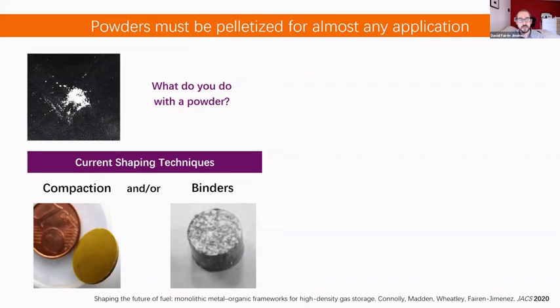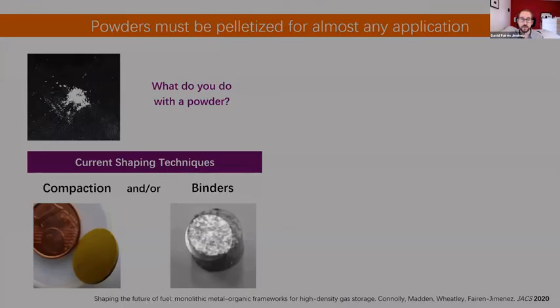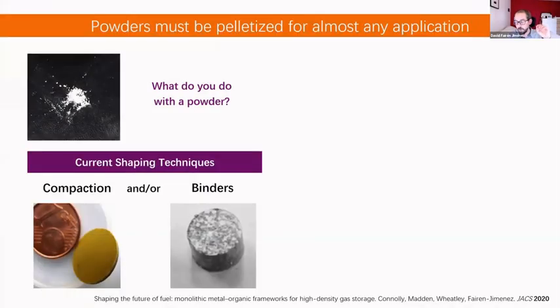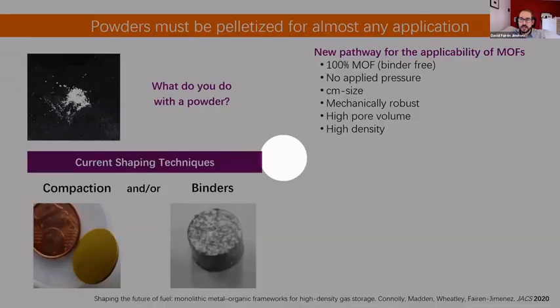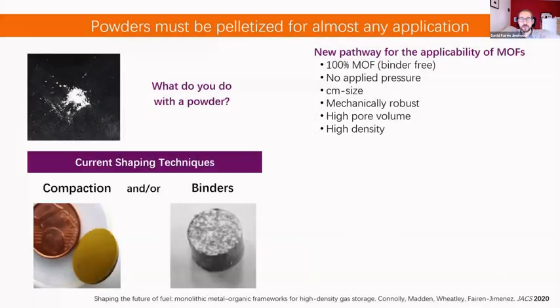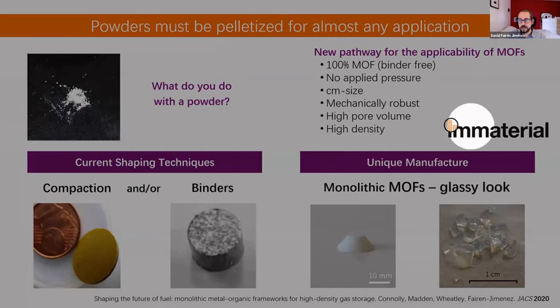If we compact this, we apply very high pressure, we collapse all the porosity of the materials. Whereas if we apply binders, we can block the porosity and still we will never use high pressure. So the material will have very low density. You remember I was talking about the density, how important this was? This is one of the cases. Basically within our work, we wanted to have this new pathway for the applicability of MOFs where we have binder-free materials, 100% MOF. We don't want to apply any pressure because we don't want to collapse the porosity. We want to be able to have the flexibility to build large structures, centimeter size pellets, mechanically robust, high pore volume, and high density. That's really, really important.